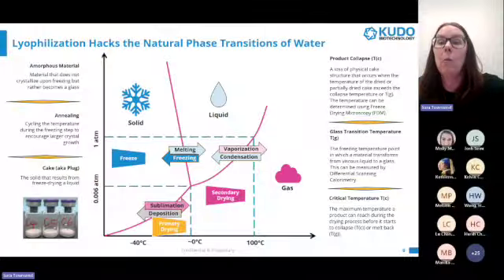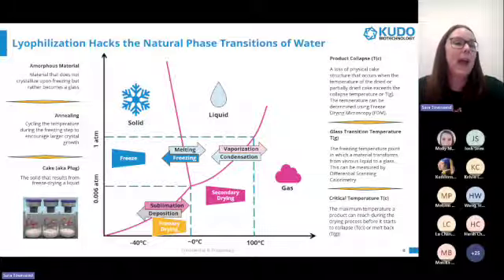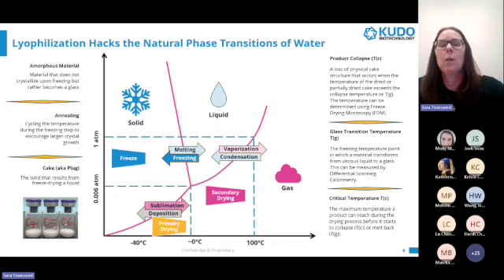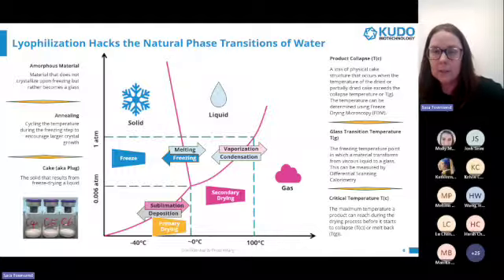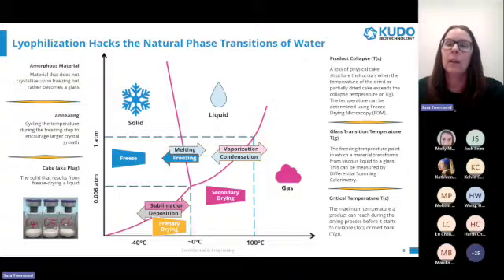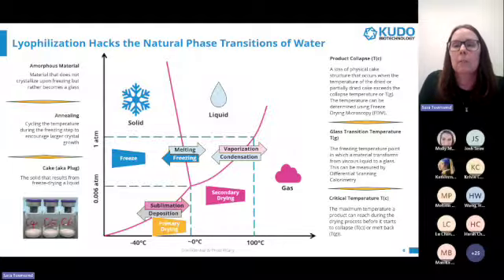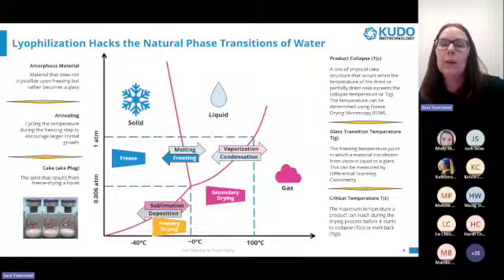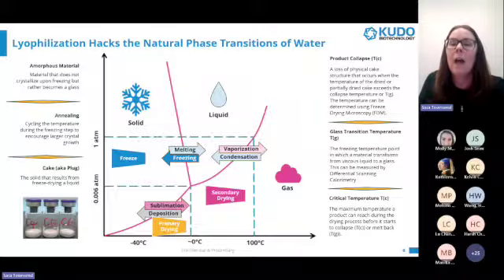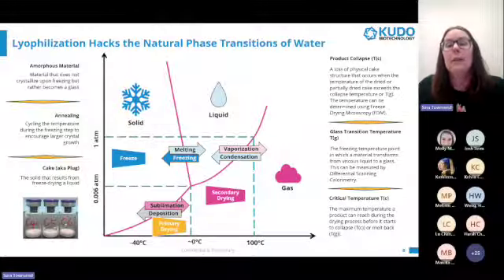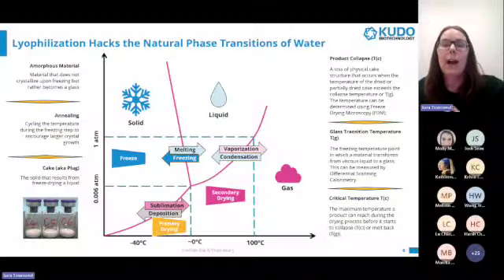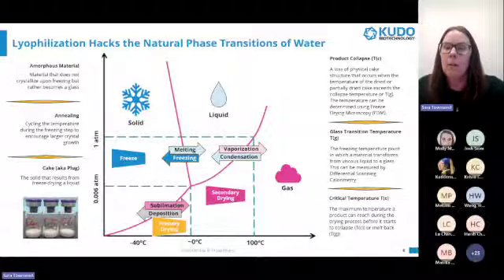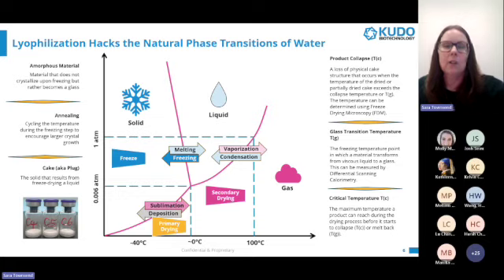We've talked a little bit about the why of lyophilization, and now we're going to cover the how of lyophilization. As we all know, at normal atmospheric conditions, water exists as a liquid at room temperature and a solid below zero C and becomes a gas above 100 C. If we lower the pressure considerably, we can skip the melt step and proceed directly from a solid to a gas in a process called sublimation, i.e., we can freeze and then immediately dry by removing the free water as a vapor. This is called the primary drying step in lyophilization.